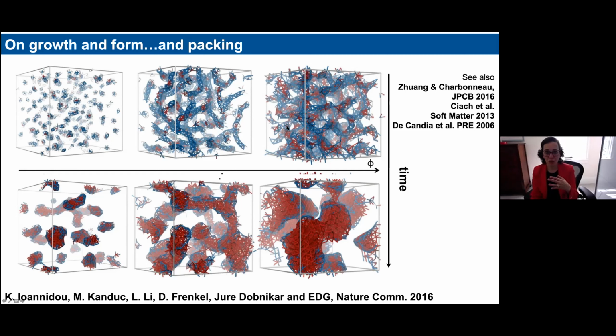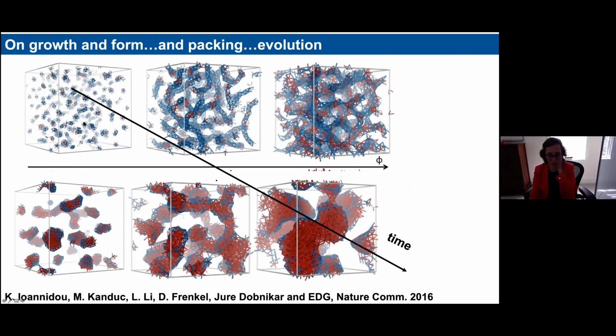It also allows me to set some preferred size of the pores, whose traces somehow remain in the following structure of the gel. On the other hand, when the interactions become more and more attractive, what I get is a gel that tends to be much bulkier. In fact, this type of interactions characterize rather the end of the hydration process, and they take over at later stages of cement hydration, they favor actually further densification of the material. And so this sequence, we can think about the sequence in time of what happens during cement hydration to go in some sort of diagonal direction this way across those processes.